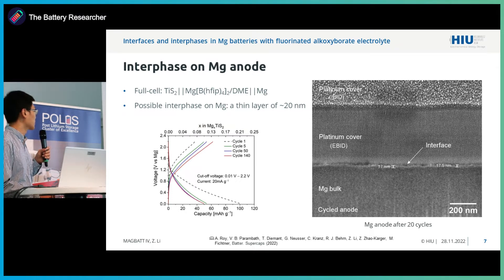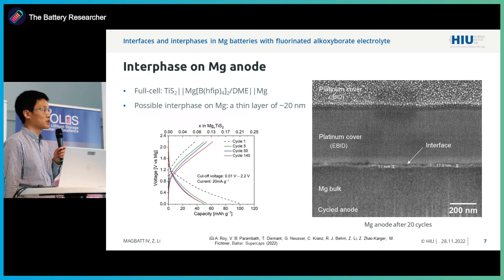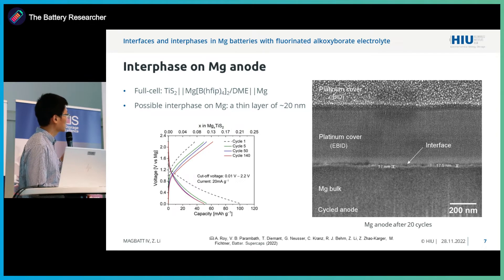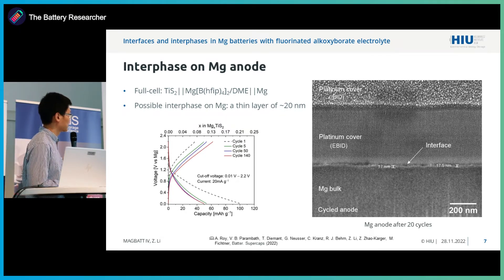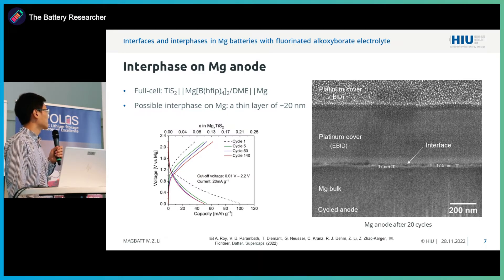We use the magnesium anode in full cell conditions with titanium disulfide as a model cathode, and this is how the cell charges and discharges. We see that after the first cycle we get stable cycling, and what we do is stop the cell at 27% state of charge, take out the magnesium foil, and do a cross-sectional image. The SEM image shows the lower part is magnesium, and the upper part we have coated with platinum to protect the interface.